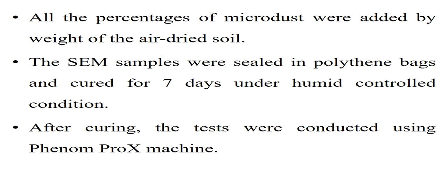Then the samples for scanning electron microscopy were sealed in polythene bags and cured for 7 days under humid controlled conditions. This is to allow sufficient time for any chemical process or reaction which will take place. And after the curing, the tests were conducted using the Phenom Pro X machine.